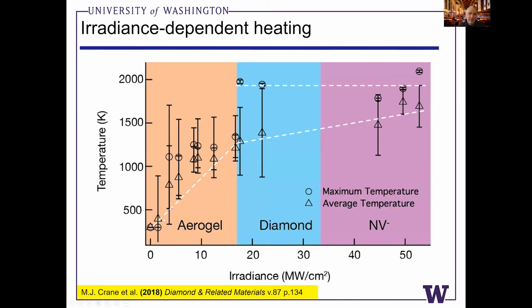And Matt Crane did a really terrific job looking at this very systematically as a function of the irradiance. And at certain irradiance thresholds, he noticed really sharp spikes in the temperature. He would see some baseline temperature around 1300 Kelvin, 1400 Kelvin. Then all of a sudden it would jump to 2000 Kelvin. And we really weren't quite sure what was going on.